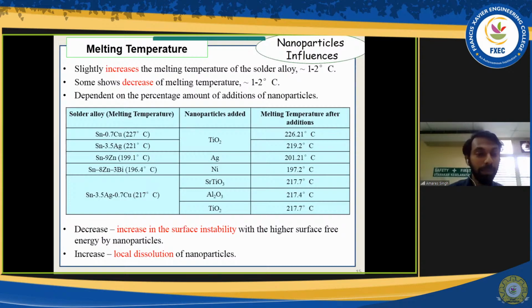If our soldering temperature is less than 250 degrees, it's okay. It's okay to use the nanoparticles because it's not elevating the melting temperature. At the same time, it would not cause any damage to the other components. So this is the important result that we see. But why is it happening?